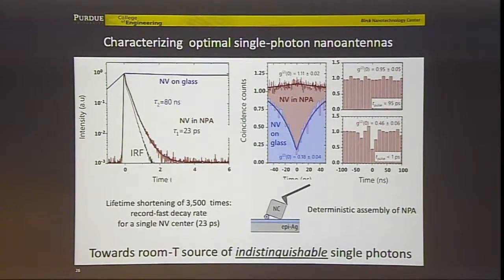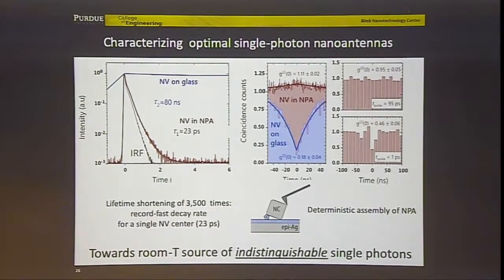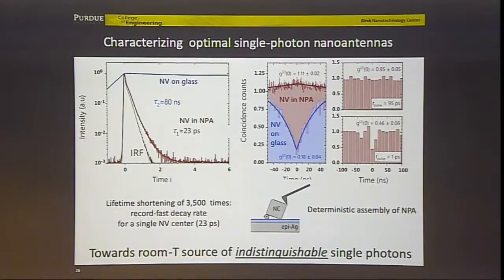The trick, though: nitrogen vacancy is not a good single photon emitter. Because of coupling to phonon degrees of freedom, the broadening, the decoherence, is huge. We don't want to beat the worst possible decoherence. We want to beat kind of modest decoherence. So the next step, which we're working on now, is to replace these nitrogen vacancies with germanium or silicon vacancies, where the decoherence time is in the range of 0.1 picosecond.